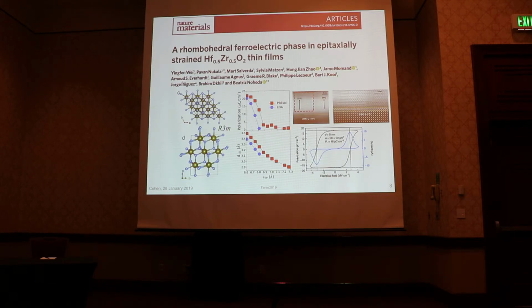Now, to make things more complicated, this is an experiment and theory paper that tried to emphasize the importance of a different structure altogether, a rhombohedral phase. And so this R3M phase, turns out, is also competitive. And they did calculations where they showed large polarizations and experiments where they found this phase in their thin film growth. So now you have a whole other story of very similar films, except that they're rhombohedral instead of orthorhombic. And so it seems like both are possible.